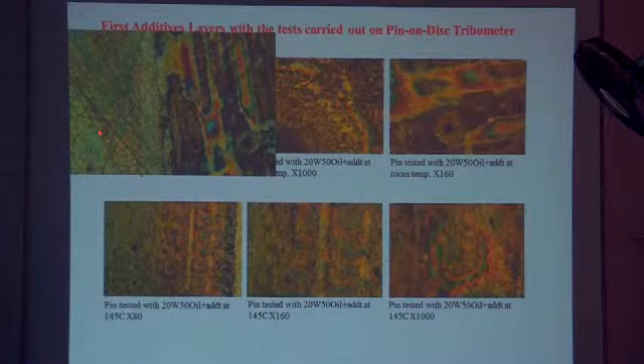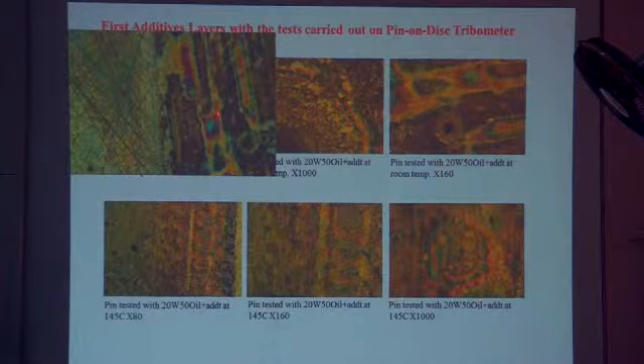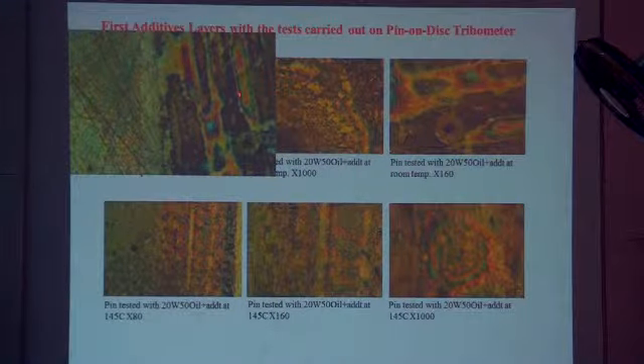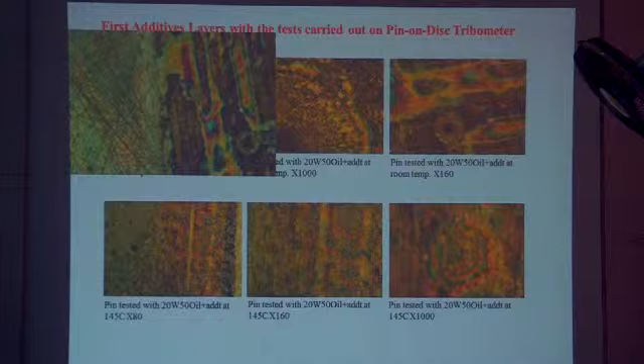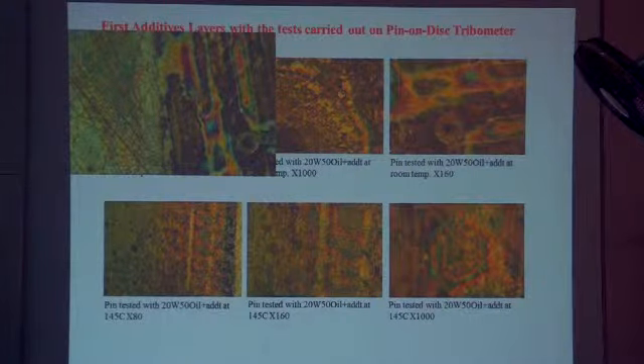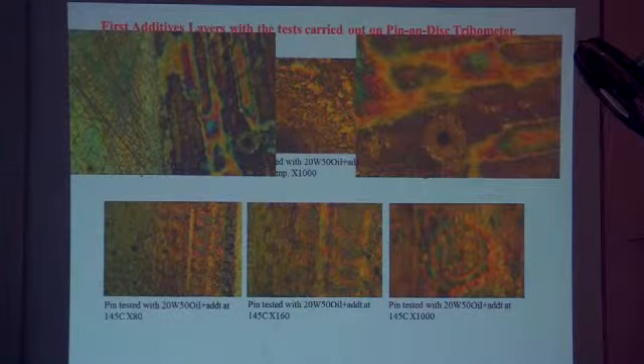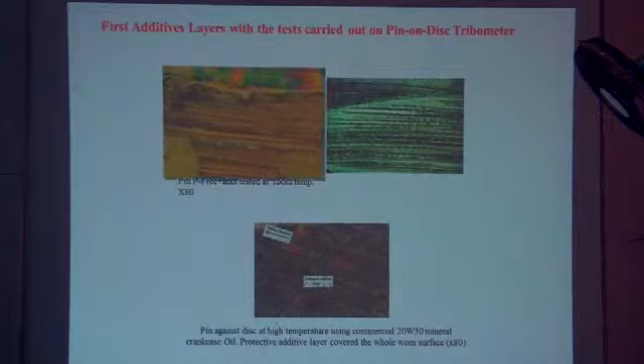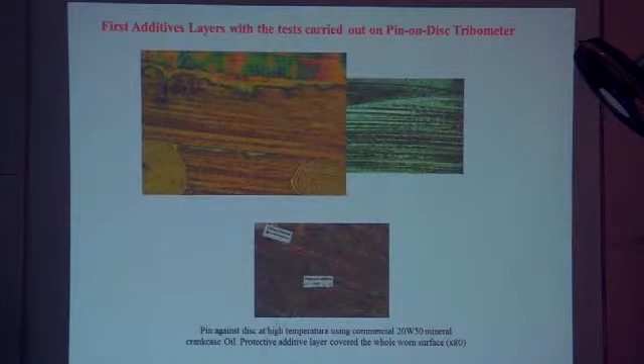You see here that the pin surface, there is no rubbing here, but the rubbed surface here and this one are slightly degraded. If you investigate that surface, you will see that additives are coming out, shown by SEM and X-ray analysis. These are examples. I published this in the Industrial Lubrication Journal at that time.